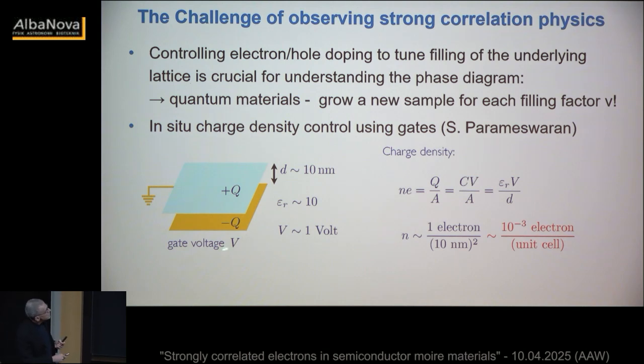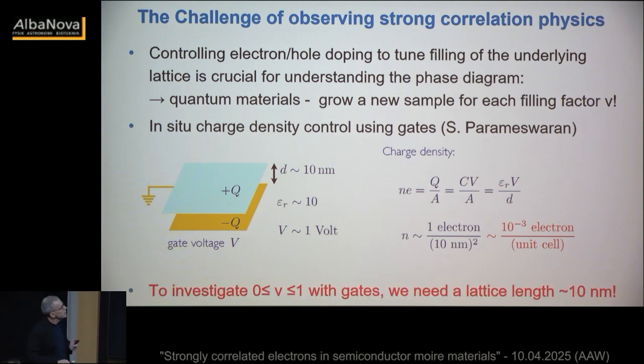Now, in such a structure, if I look at the electron density, then going through typical dielectric constants of about 10, what I will find is that the maximum density I can get is about 1 electron per 10 nanometers squared. So which tells me that if I have a lattice where the lattice period is about 10 nanometers, then I can actually control the charge density or the filling factor anywhere from 0 to 2, 3, etc. Okay, so that's the idea that in order to be able to have this electrical tunability, we need a new lattice length scale that is on the order of 10 nanometers. It doesn't have to be 10, it can be 5, but something that is at least an order of magnitude larger than the actual intrinsic lattice length scales, which is about 0.2 nanometers.